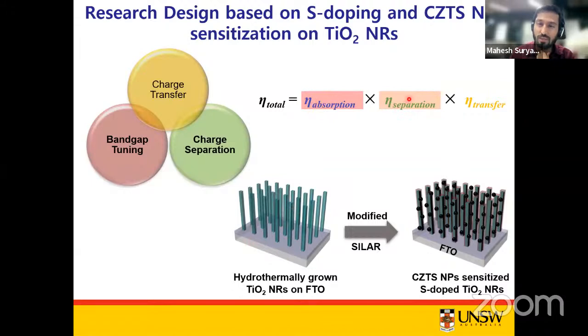We can also improve the charge separation by utilizing the approach of sensitizing these TiO2 nanorod arrays. When we sensitize with CZTS nanocrystals, there is a formation of type 2 heterostructures between TiO2 and the CZTS, which helps us improve the charge separation in CZTS nanocrystals. That's how we designed our research idea, and we carried out the experiments in the lab, and we achieved improved performance, which I will explain in my next slides.